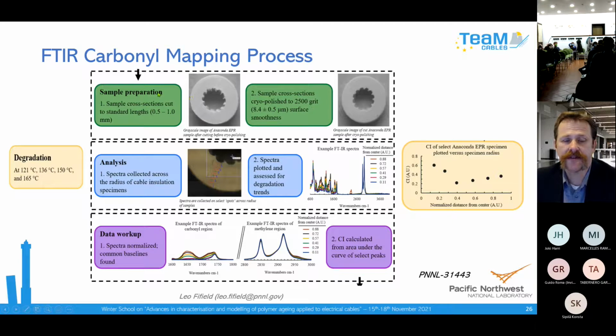Here's a process for the FTIR microscope where we took a cross-section of a sample, polished it to get a nice flat surface, and then measured the infrared spectra at various locations through the thickness. There's a peak that corresponds to the carbon double bond oxygen, the bond that forms with oxidation, and that peak increases with oxidation. The carbon-carbon and carbon-hydrogen bonds correspondingly decrease in quantity. The ratio of those two is a carbonyl index, and that's a way to trace oxidation. We're able to do it with this microscope as a function of location through the thickness.